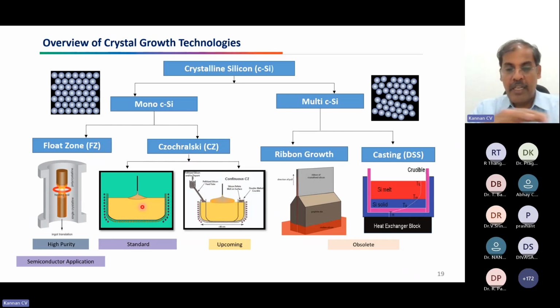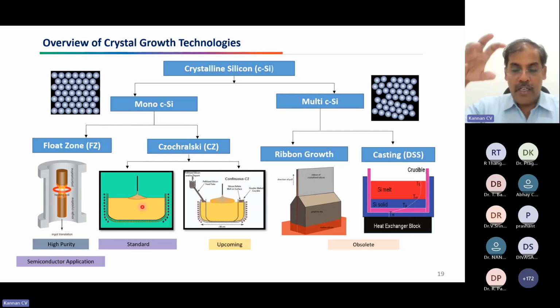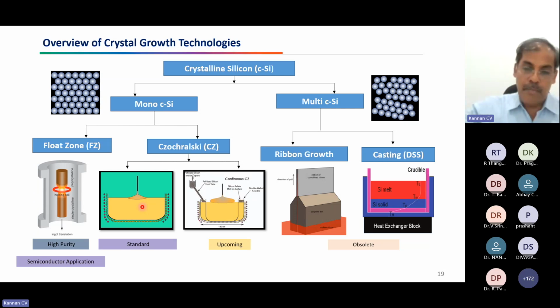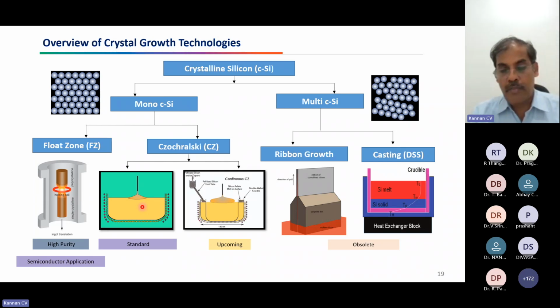So that they maintain the melt level, and continuously you can grow the crystal, then pour the material parallelly and melt it, so that you can maintain the melt flow, solid liquid interface level, where you can grow multiple crystals. That way you can minimize the downtime. You can produce many crystals in a small period of time. In that way, your productivity will improve automatically.